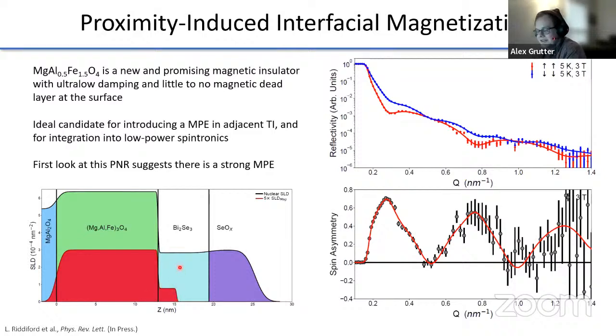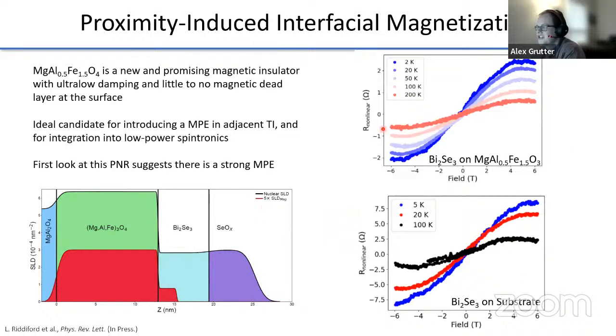Now, Lauren Riddiford, the student leading this study, who did a really nice job, decided to double check this with transport measurements. And so what she did was take anomalous Hall measurements on bismuth selenide on top of magnesium aluminum ferrite. And so what she finds is a nice nonlinear Hall effect that looks an awful lot like a really low coercivity magnetization where you have some sort of saturation. And so this looks very much like what you might expect from some sort of anomalous Hall effect induced by a magnetic proximity effect, which is in agreement with this little bump here, right? That looks like a proximity effect in the bismuth selenide.